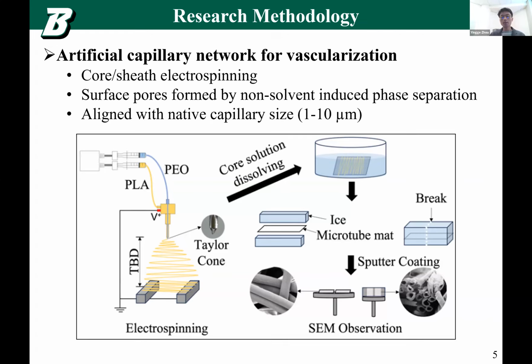We got the tubes. Now we have to demonstrate we got the tubes. That's the most difficult part that we met, because the polymer is really soft. You can stretch it, but you cannot break it. If you use scissors to cut it, the opening will be closed. But we want to get a microscope image. So we put the collected microtube sample, which is in a mat form, into a sandwich structure clamped by ice.